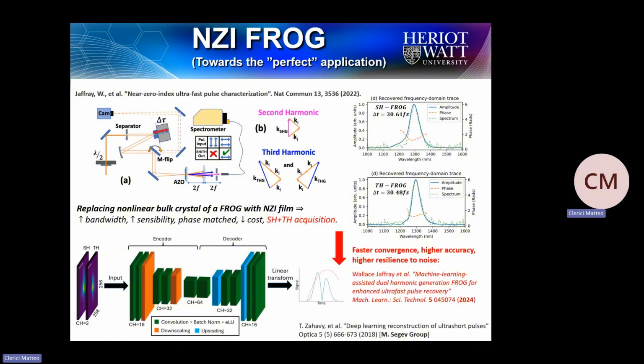And in this system, by replacing the standard bulk nonlinear crystal that is cut for phase matching and for bandwidth optimization with 250 nanometers of our low index material, we substantially improve, by a large margin, all the basic parameters of the original system. So bandwidth, sensitivity, and also with the additional advantage of eliminating phase matching requirements because of the deep subwavelength nature of the film. Everything was phase matched by nature. In addition to that, we were able to record both second and third harmonic at the same time, and so we had both second and third harmonic FROG combined.